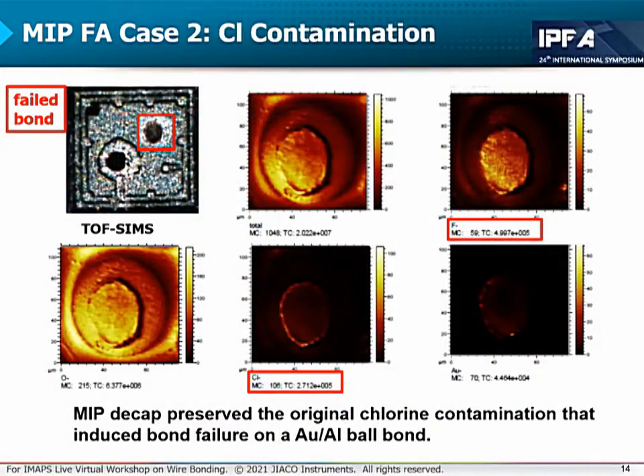Next failure analysis case is halogen contamination, which is a frequent cause of corrosion-induced bond failure. Acid decapsulation and halogen-containing plasma can introduce foreign halogen, but they can also remove the existing one. So with these two methods, it is actually impossible to tell where the detected contamination comes from.